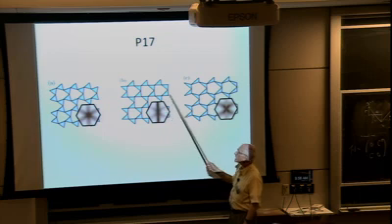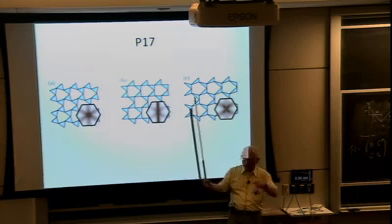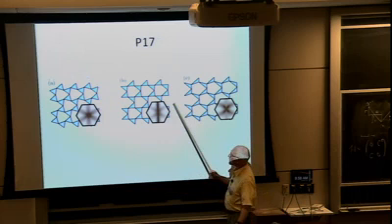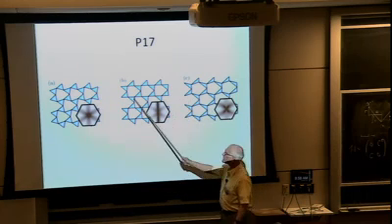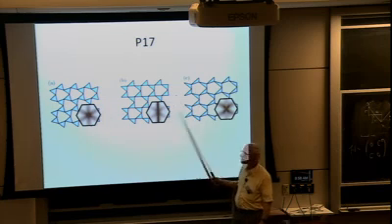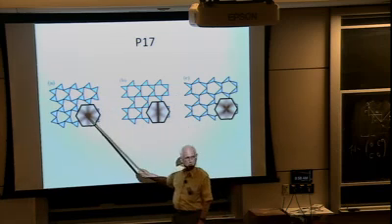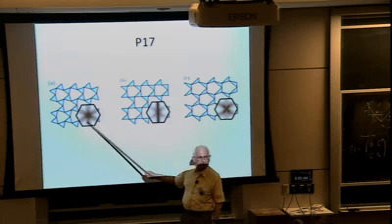So the parallel lines in this direction give me states of self-stress along here and a line of zero modes like that. And now I want to do the same sort of thing that we did for the polyacetylene, which is I want to distort the lattice so that we get rid of this straight line and we have things that look different on the two sides. So going this direction, we get the Kagome lattice and we have the gapless spectrum.